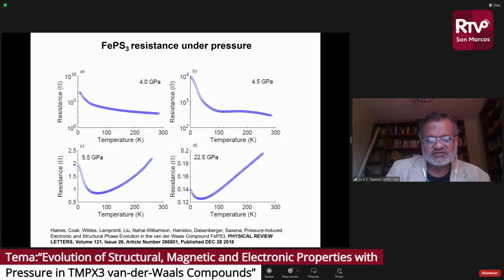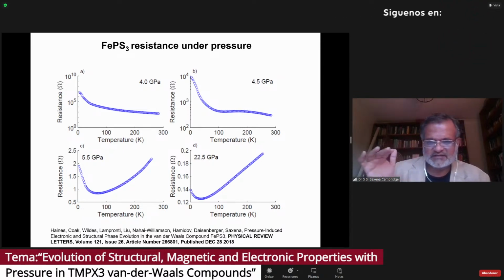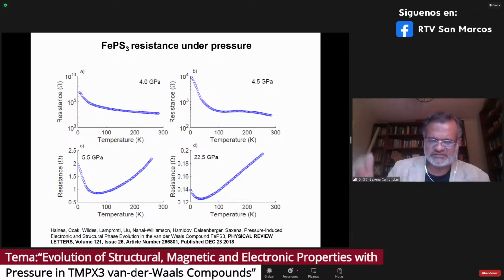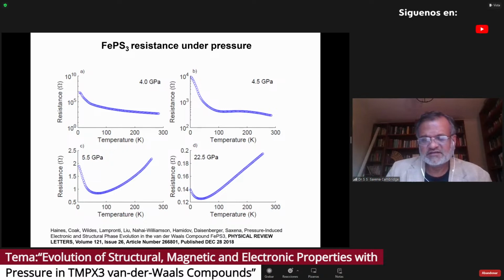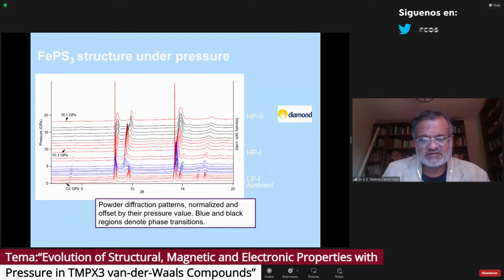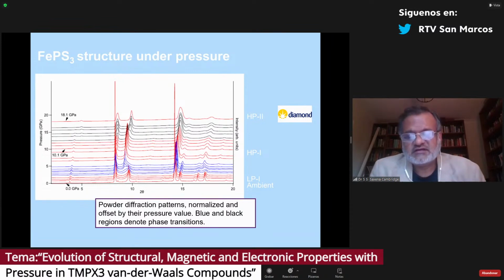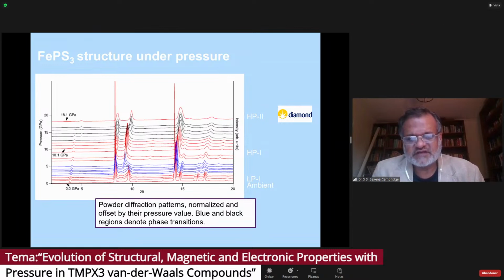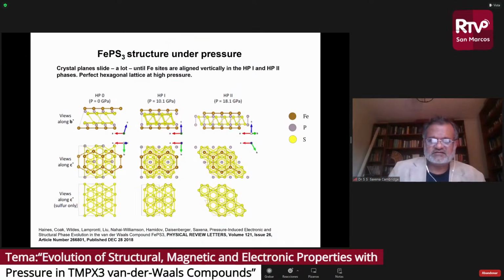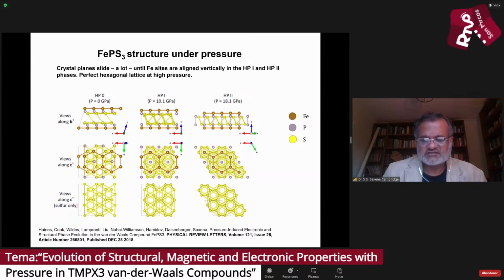However, what was becoming quite prominent, because these materials have already been shown to be single layer magnets or magnetic graphene type, was that a lot of interest was emerging, and people were trying to understand the photonic or electronic properties of these materials as well. So we conducted high pressure, or one could say ultra high pressure, X-ray diffraction measurements, powder diffraction, and we saw some quite intriguing behavior in these materials. And what you will see here are the results of these kinds of studies plotted here.